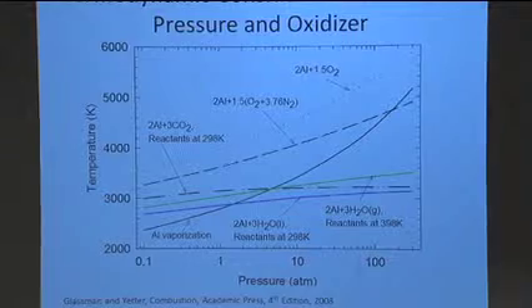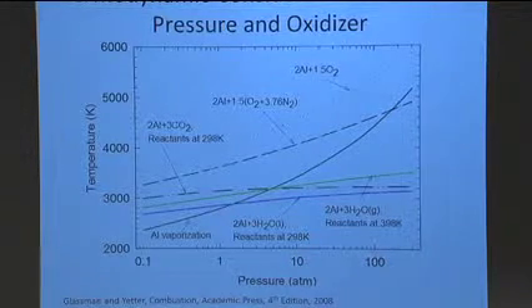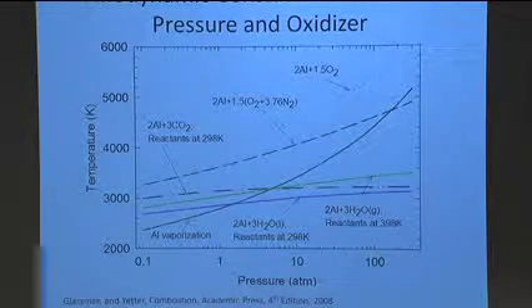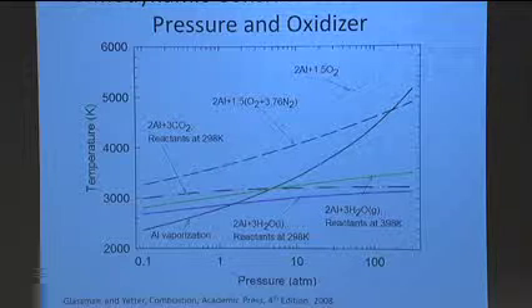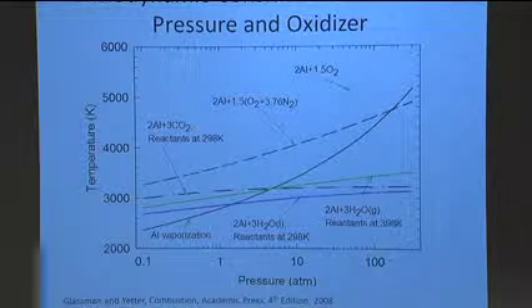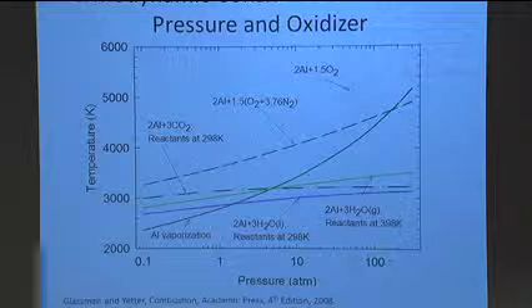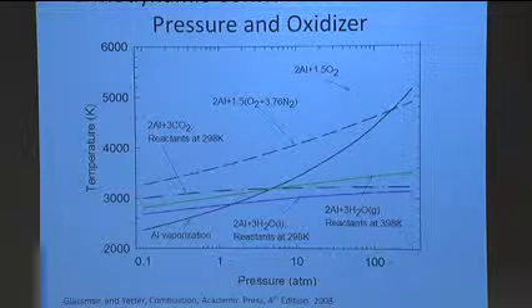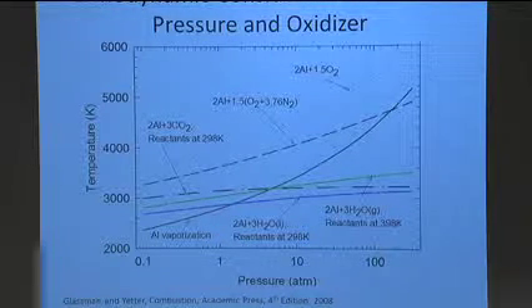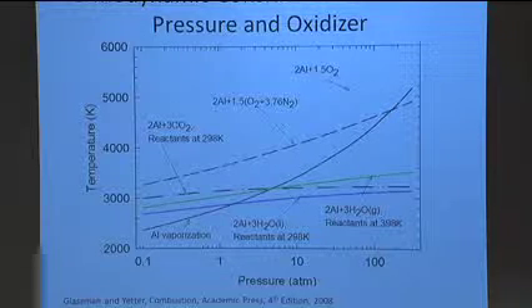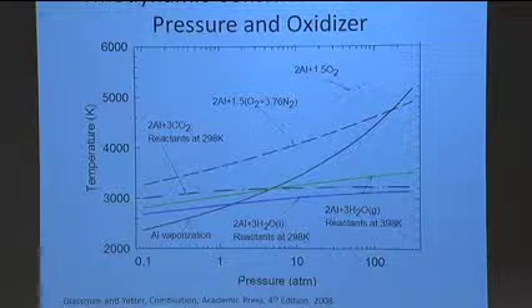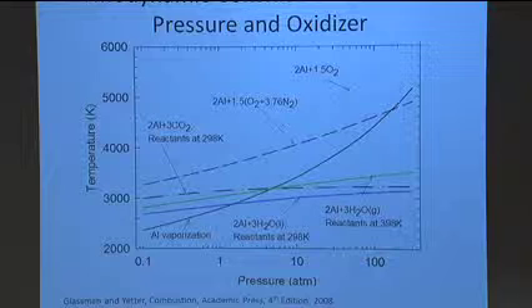So much like a hydrocarbon droplet, I'm going to form an envelope. If this is a large particle or a bulk material, I'm going to have basically heat being transported back from where the reaction occurs to the surface. It's going to vaporize the aluminum, and the aluminum is going to vaporize away from the surface and react with the surrounding oxygen. What's kind of interesting then is if I start increasing the pressure in systems.